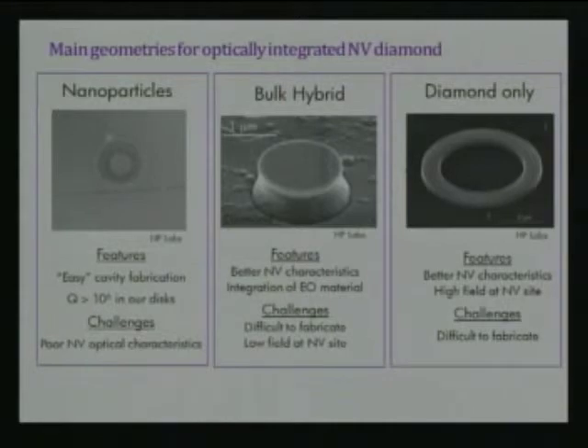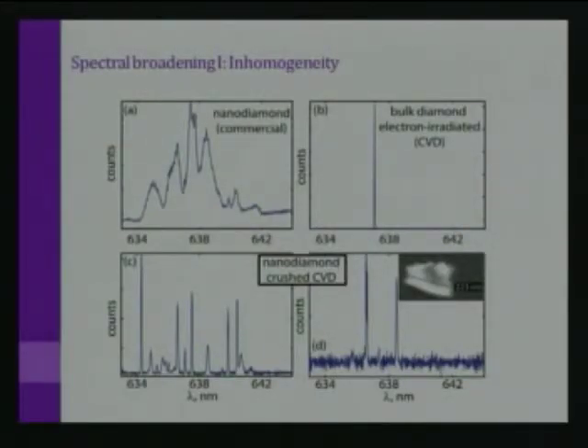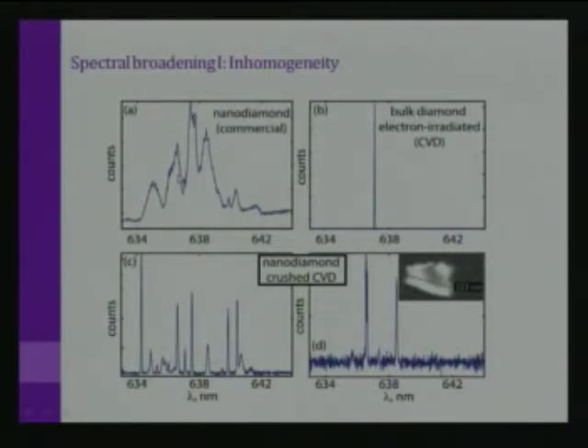What do I mean by poor spectral properties? Here you see four spectra of NV centers in different samples. In commercial nanodiamond, the zero phonon line peaks are spectrally huge — the NV line diffuses back and forth during the measurement, meaning photons emitted at different times won't be indistinguishable. This is why we don't use nanodiamond. More promisingly, an electron-irradiated CVD sample shows roughly 1,000 NV centers all emitting at approximately the same wavelength. I then tried grinding single crystal diamond with a pestle and mortar and centrifuging to get small particles. Individual lines were still quite sharp in particles as small as a couple hundred nanometers, but the strain inside nanocrystals caused them all to emit at different wavelengths — a problem we can't tune away practically over tens of terahertz.